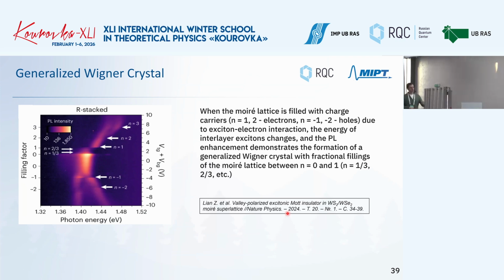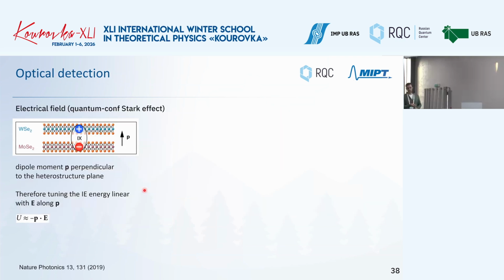The reason why I'm showing this is that we were able to reproduce it already 1 year ago, and we moved a bit further with this, but the general concept is as demonstrated here. So you have this image of the interlayer excitons. Interlayer excitons have some specific photon energy, so they emit at a specific wavelength. And when tuning the gates, as we see here, the displacement field or carrier density, you can see that the interlayer excitons are not just representing some straight line as here.